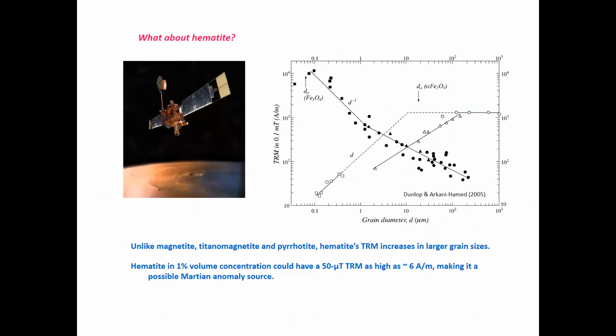Well, what about hematite? We have to get to hematite. Hematite, unlike magnetite, which has this lovely continuous decrease in virtually all properties, here it's the TRM intensity, as you go up in grain size, hematite counterintuitively goes exactly the opposite way, with the fine grains having a weak TRM and the large grains a large TRM. You'd wonder how that could possibly happen. I mean, these large TRMs are sufficiently large to make hematite a very viable source of magnetic anomalies on Mars. And these are, as you know, massive magnetic anomalies.